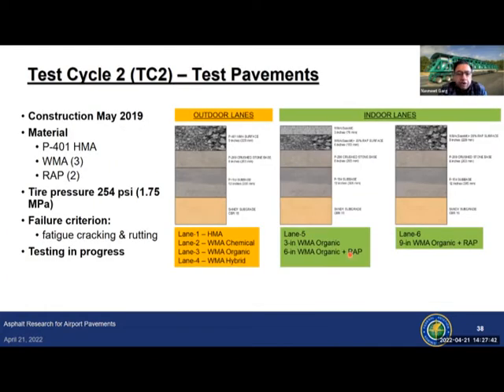We changed our pavement cross-sections compared to test cycle one. In test cycle one, we had a 5-inch thick asphalt surface, 12 inches of crushed stone base, and 12 inches of sub-base, which was also crushed material. And our subgrade here is a CBR 15 sandy subgrade. So we increased asphalt thickness to 9 inches. So we removed 4 inches of P209 crushed stone base. So all the lanes had a 9-inch thick asphalt surface and 8-inch thick crushed stone base over a sandy subgrade.